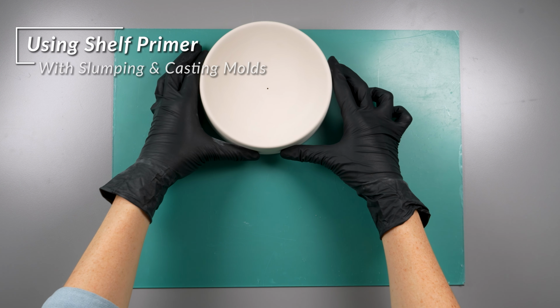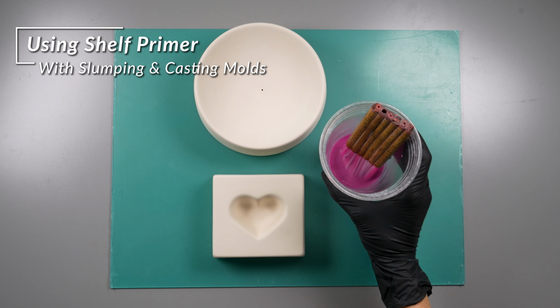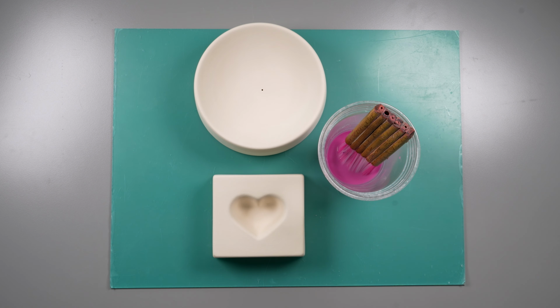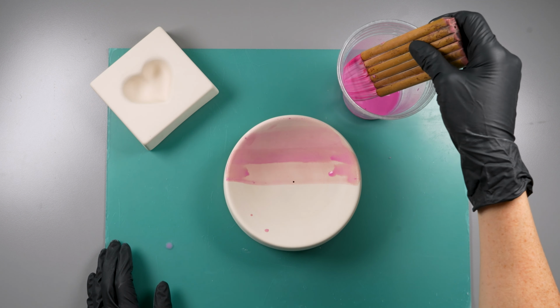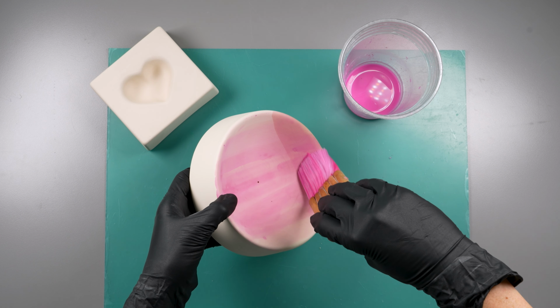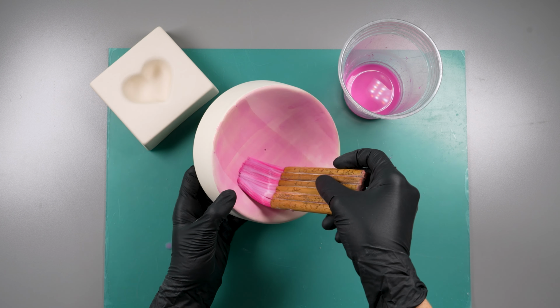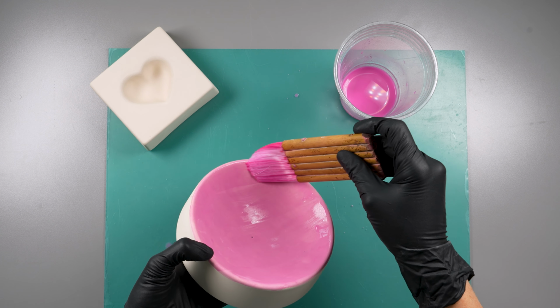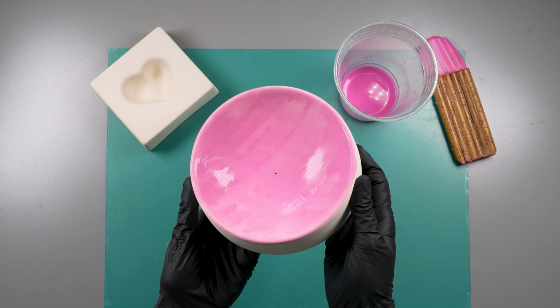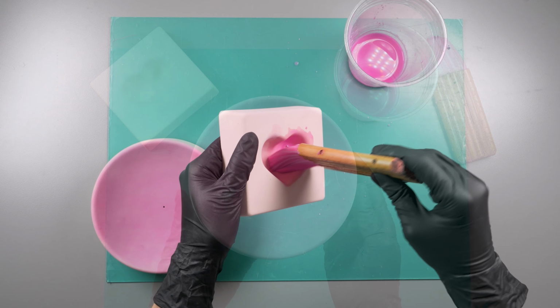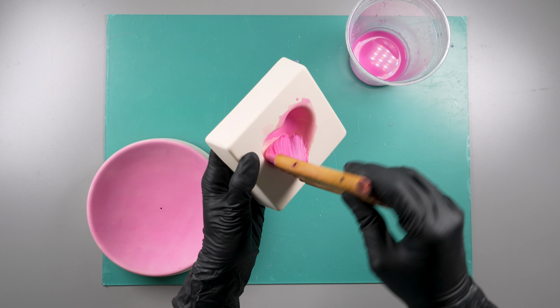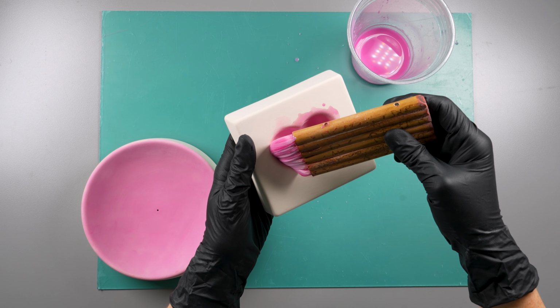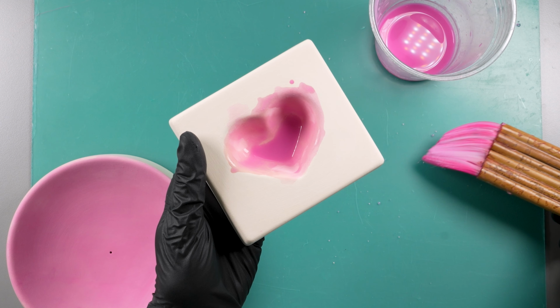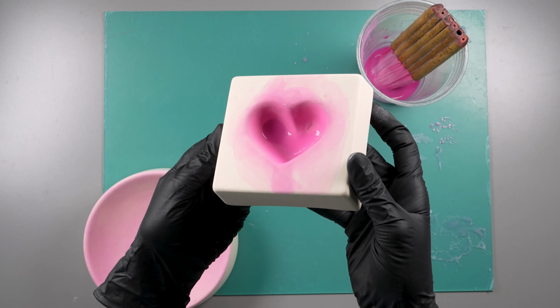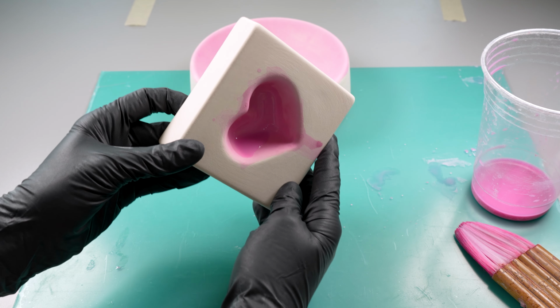The process of preparing a slumping or casting mold for firing with shelf primer is largely the same as for a kiln shelf. Several coats should be applied in the same manner as previously shown, with each coat running in a new direction. One difference from shelves is that mixed shelf primer tends to pool in the bottom of concave molds, especially casting molds. Take special care not to let it dry there, since an extra thick section of primer will not only affect the shape of the fired glass, but can also become difficult to remove post-firing. Slowly tilt the mold in different directions to help even out the coating.